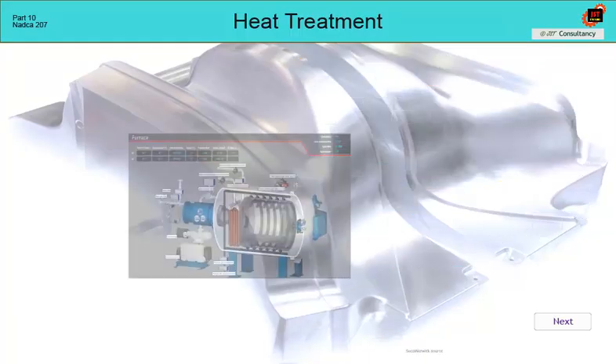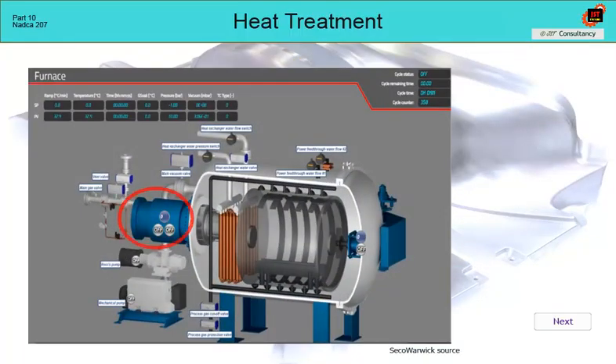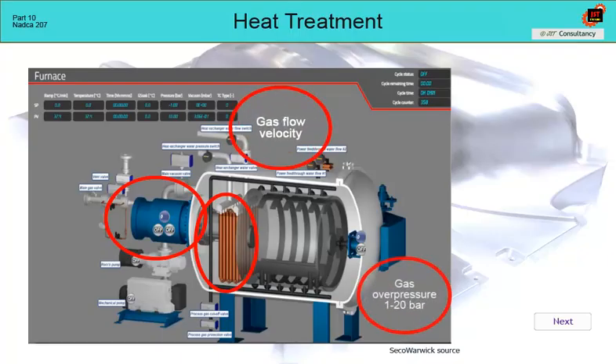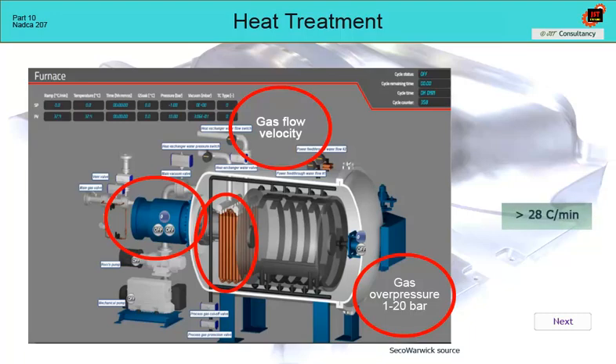The cooling capacity of the furnace is determined by the fan power, fan speed, heat exchanger size, gas velocity, and overpressure. Even with the best furnace design, every device has its limits in cooling rate. If the mold inserts are too large, the cooling rate of 28 Celsius per minute may not be achieved.